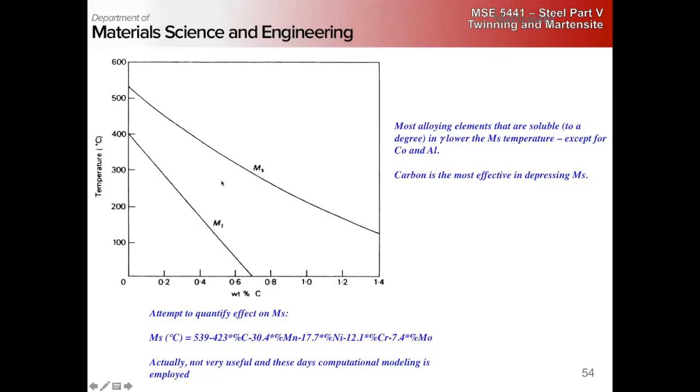Yeah. When you have 0.3% carbon, why do you still have a martensite start? Because martensite forms in other systems like iron nickel. So with other alloying elements, you can have nominally a steel composition, right? And then keep everything else fixed and remove the carbon. It's arguable when you get down to it, right? Are you still a steel? Most people would kind of say yes, right?